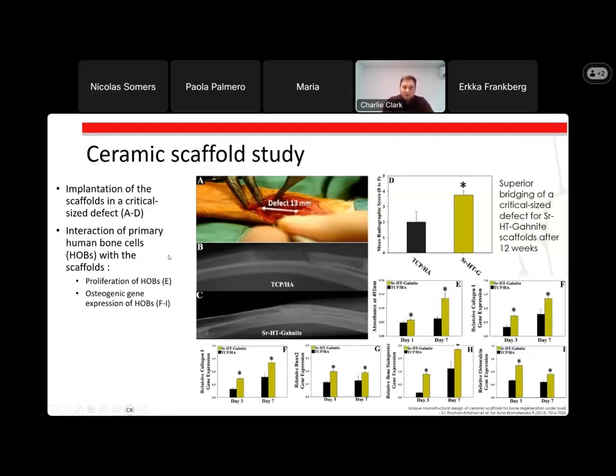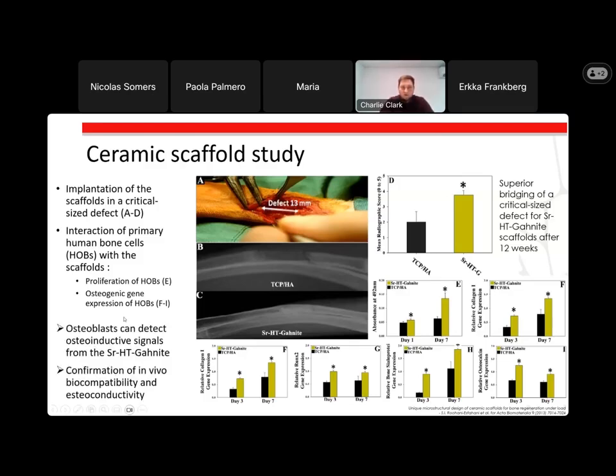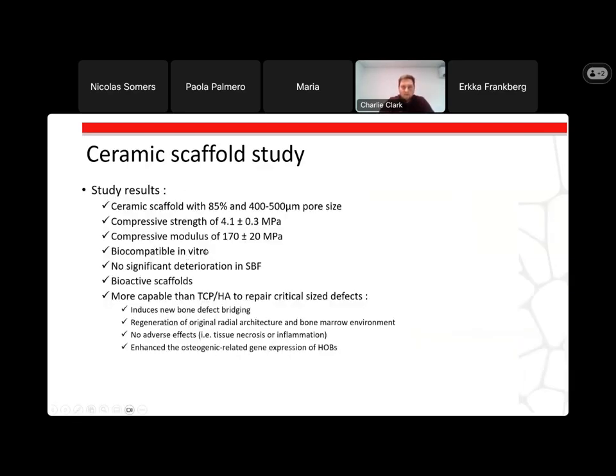Then they also did some tests with the interaction of the material with primary human bone cells, looking at the proliferation and the osteogenic gene expression. What they found was that the osteoblast can detect the osteoinductive signals from the new material, which also explains the bridging superiority compared to the other material. And there's also confirmation of in vivo biocompatibility and osteoconductivity, which means that this material could be used in implants.